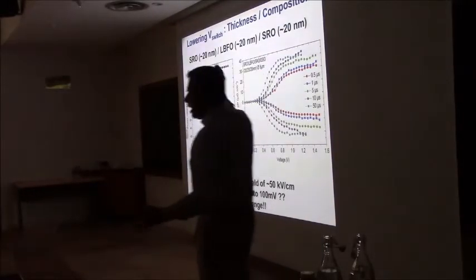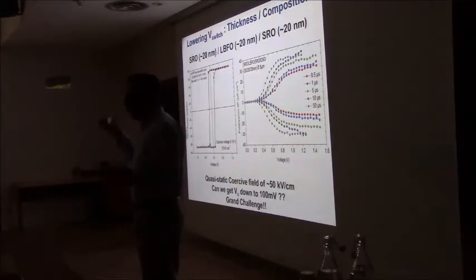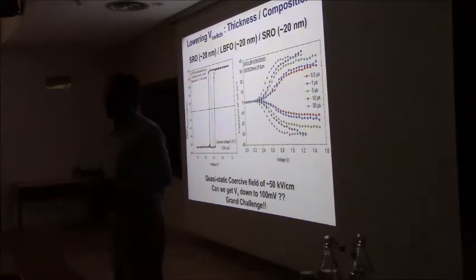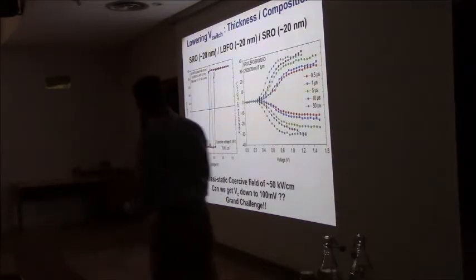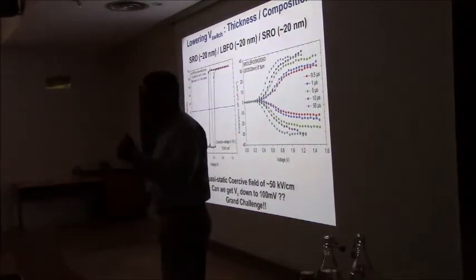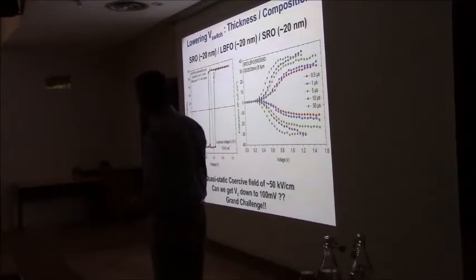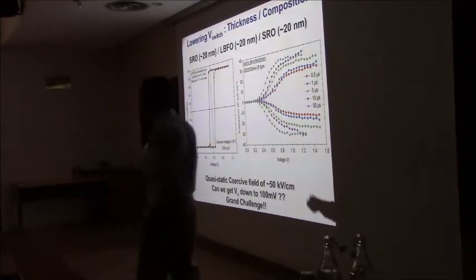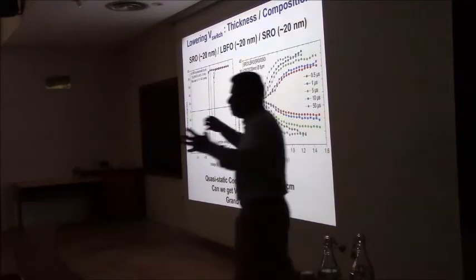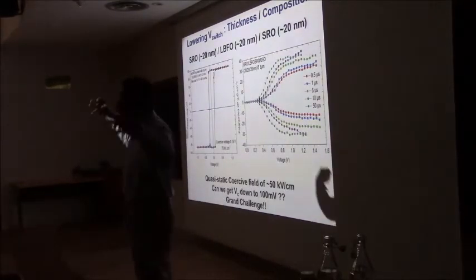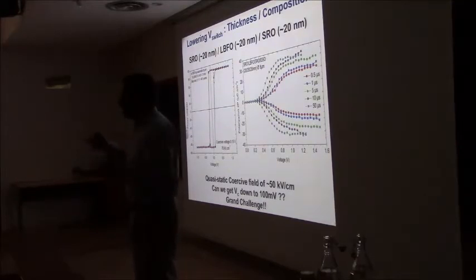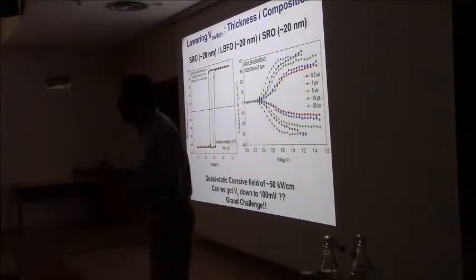One is, obviously, I want to reduce my thickness. We went from 100 nanometers. We're now playing with 10 to 20 nanometer thick samples. By itself, it's a materials challenge. We have to make high quality materials. So the thing that we see, both by reducing thickness and chemically doping bismuth ferrite, in this case we put lanthanum into it, typically about 10 to 15% of lanthanum. How do you take bismuth ferrite, which is a very hard ferroelectric, large polarization, and soften it up? And in the PZT literature, that typically is done by putting zirconium into titanium and making it go towards a morphotropic phase boundary, making the material softer and softer. We're trying to do something very similar here.